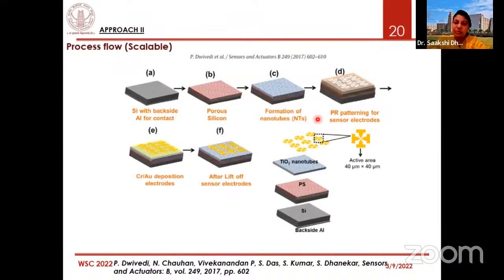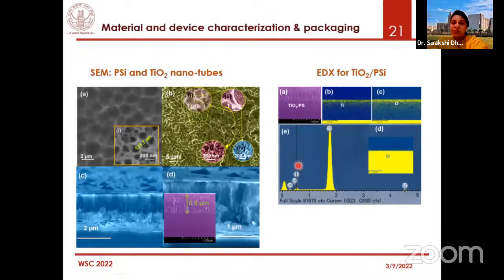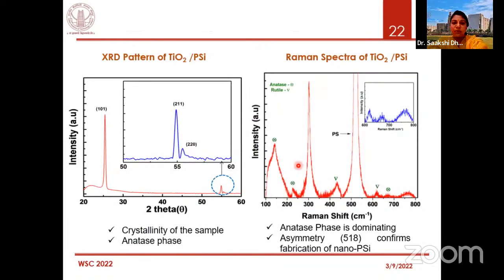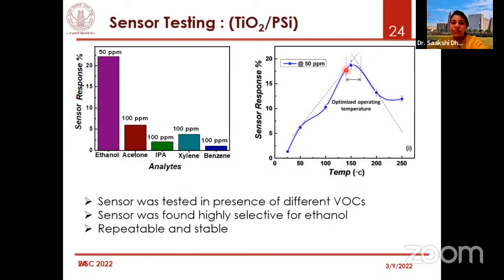So then we tried another approach. What we did here, we grew titanium dioxide nanotubes, which were a little thicker than the previous version. And here we did a lot of optimization in terms of contact pad size, and, again, it's nanotubes, whether they are uniformly spread over the surface, and all that characterization was done to understand what we are achieving. And what we realized here was that we could see change in response, but at higher temperature. So the sensitivity improved drastically. What we lost really was the operating temperature, which we wanted to be room temperature, so that we don't have to integrate a heater and then have a bigger battery to run the system.